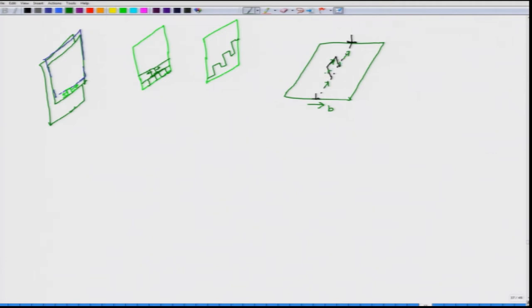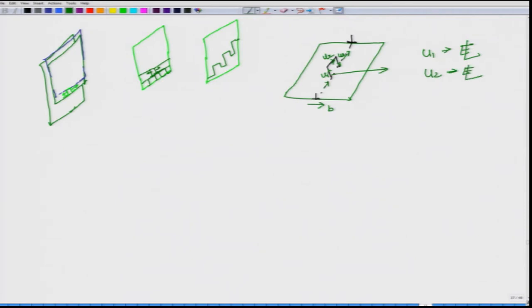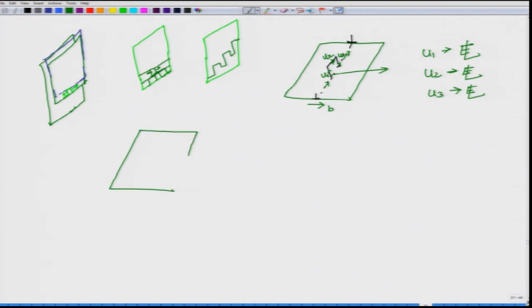In this particular case, what do we see when a jog is formed on an edge dislocation - what will be the characteristics? Let us say this is u1, u2, u3. What is the character of u1? u1 is still an edge dislocation because the Burgers vector is perpendicular to it. What about u2? u2 is also an edge dislocation as the Burgers vector is perpendicular. What about u3? This is also an edge dislocation. Now, if you remember edge dislocation has higher energy than screw dislocation, so having a mixed character would ensure that the energy is minimized. In reality what you would get is something like a rounded character.